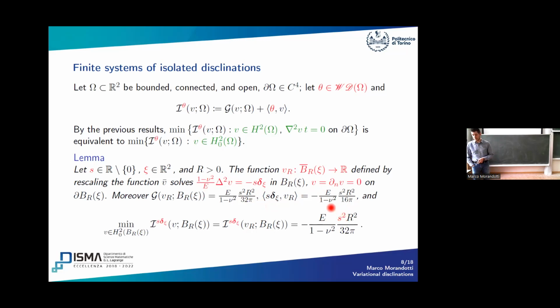Actually, no, sorry, twice as much. Okay, so twice as much. And so we can compute explicitly the minimizer for this case, and it's going to be given by this quantity here, which has 2 particular features. It depends on the Frank angle with the square of it, which is fine because we wouldn't really care if it's a positive or negative disclination. The stored elastic energy measures the presence of the defect, and we're happy with that.